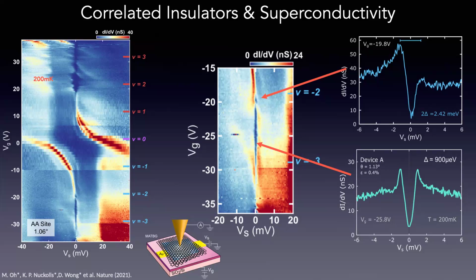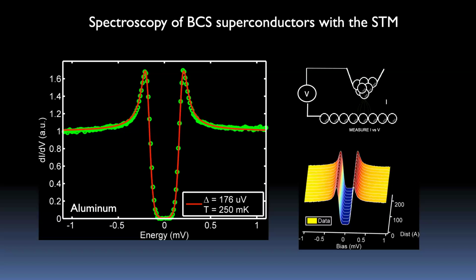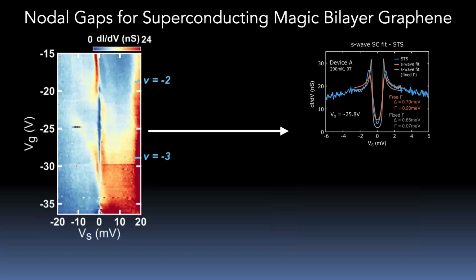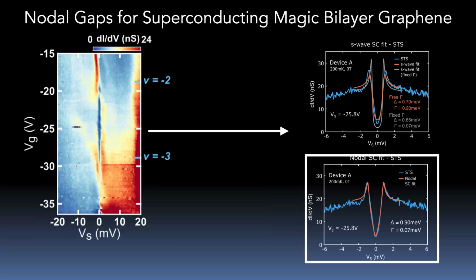So obviously, you can look at the superconducting gap in the same instrument. You can put a piece of aluminum, which has a TC of 1 Kelvin, and measure its density of states. You get a nice BCS density of states, s-wave gap. But in this system, that's not what we get. You get a V-shaped density of states, which is indicative of a nodal gap. And if you try to fit it with your s-wave model, you have to add broadening, that's just obvious.